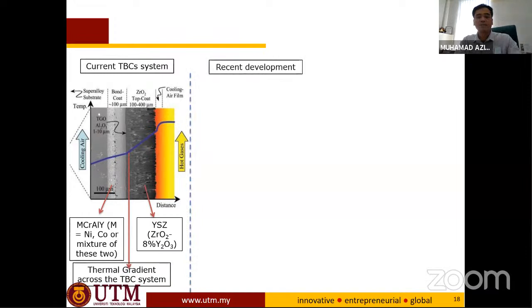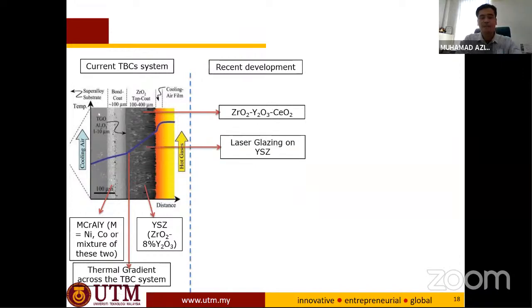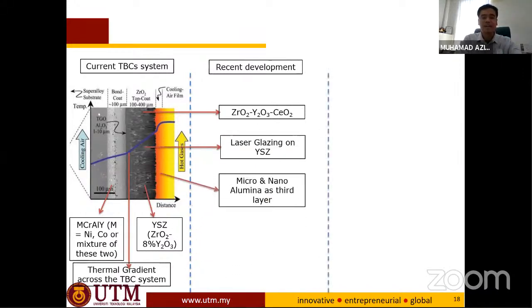This is typically what we have in recent development. They add a ceria, CeO2, on top of the YSZ. They glaze it, as I mentioned earlier, with laser. And they can also have micro and nano alumina as a third layer. So you can have another layer to reduce the diffusion of oxygen, because oxygen from the outer side will diffuse up to the metal. If it diffuses to the metal, the metal becomes oxide, okay? So how do we handle it? We coat another layer here, the third layer, like alumina.